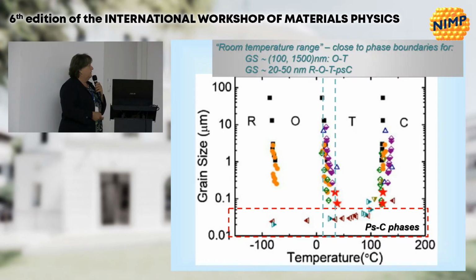Another observation is related to the so-called room temperature, which is a very badly defined temperature, because what does room temperature mean when, as you can see, we are close to the orthorhombic to tetragonal transition for grain sizes above 100 nanometers, while in this range we are practically close to all the transitions? Practically, here they merge in the same point. So when one reports properties at room temperature, one should be aware that it might be here or close to this range, and practically the system is close. Even our barium titanate, that everybody believes is tetragonal, is practically close to a range of phase instability.